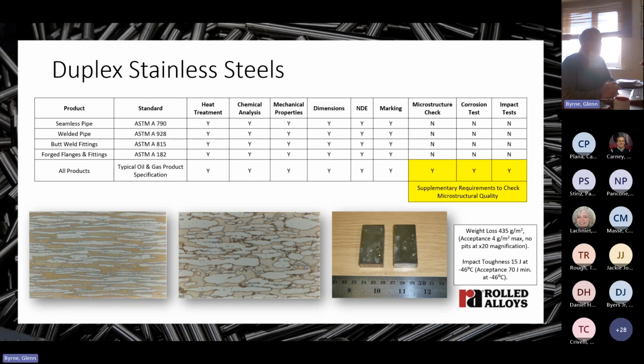Duplex stainless steels consist of two phases, ferrite and austenite, and they're in roughly equal proportions in the steel. This image on the left here is the transverse section through a plate that's been polished and etched to show these two phases. The ferrite is the darker of the two phases, and the austenite is the lighter of the two phases. The austenite is relatively weak, but it's very tough, and the ferrite is very strong but rather brittle. So by metallurgically engineering roughly equal proportions of each phase, you get the best combination of strength and toughness. Also, by alloying with enough chrome, moly, and nitrogen, you get good corrosion resistance. And it's that combination of properties that make these steels so attractive.